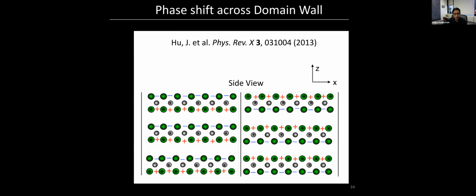So this would be very hard to probe unless you looked at a monolayer. However, one interesting thing about this idea is that if you could find a sort of domain wall in the system where the top and bottom seleniums are flipped, and this is what I was talking about at the beginning of the talk, you should actually expect to see these kinds of domain walls, then you naturally have a pi phase shift in the superconducting order parameter.